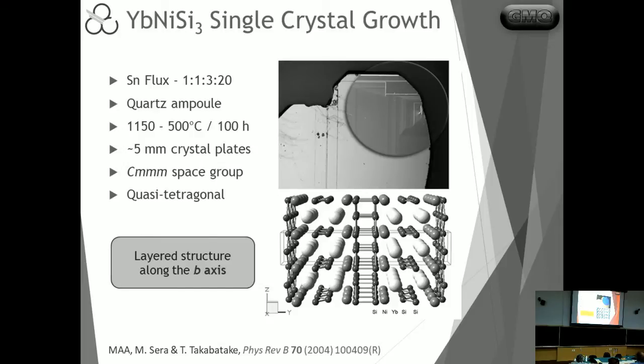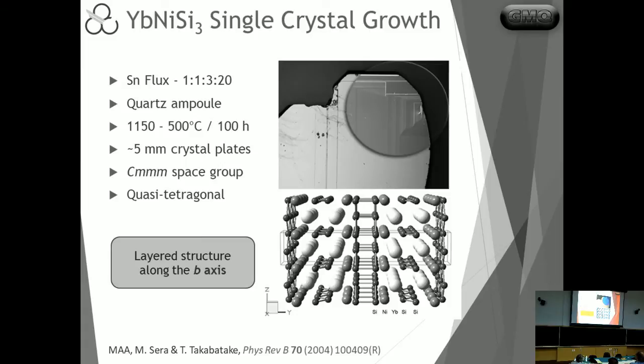And so then we proceeded to characterize these crystals. First of all, the crystallographic aspects of them, we found out that these are an orthorhombic structure within the CMMM space group. But the A and C lattice parameters are very similar to each other, so these are a quasi-tetragonal structure. And there's a layered structure here, alternating silicon, nickel, and ytterbium along the B-axis of the structure.